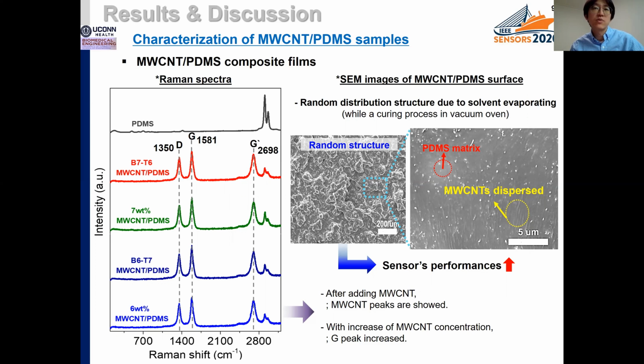Also, the degree of MWCNT dispersion and the surface morphology of the composite materials were investigated using SEM. As a result, when you look at the SEM image, we confirm that MWCNTs were dispersed in the PDMS matrix, and the composite film has a random distribution surface structure, which might be caused by the IPA solvent evaporating during the curing process.